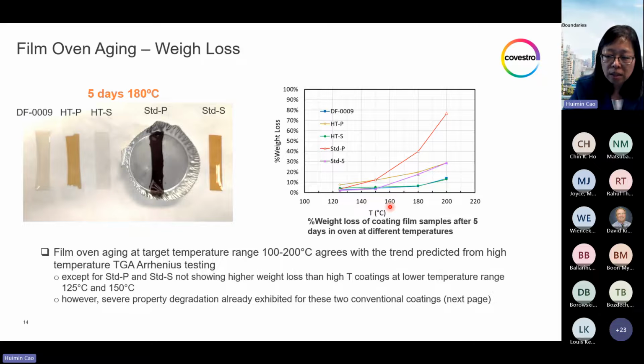And this is only the case in oven testing, not in TGA. Because in TGA, the standard coating, even at this relatively low temperature, still shows the conventional coating has significantly higher weight loss than the high temperature coating. And the difference is in the oven, at these relatively lower temperatures, there still might be some moisture content left, while the TGA is dry air. So the weight loss from the oven test is no longer a proper parameter to evaluate the coating degradation at these relatively low temperatures.